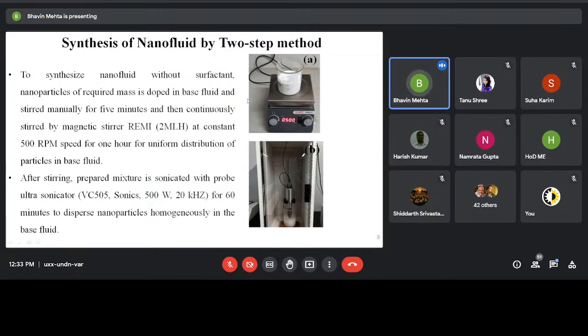Then for synthesis of this nanofluid, the fluids were prepared with the said volume fractions using the surfactant as well as without using the surfactant. The aim of the study is to check the effect of surfactant on the stability, and also to find the thermal conductivity and viscosity. For that, we used a magnetic stirrer, and the nanoparticles were added to the base fluid and constantly stirred for 1 hour at a constant speed of 500 RPM. Then with the help of a probe sonicator, VC505, with 500 watt rating power and 20 kilohertz frequency, it is sonicated continuously for 60 minutes for proper dispersion of the nanoparticles in the base fluid.